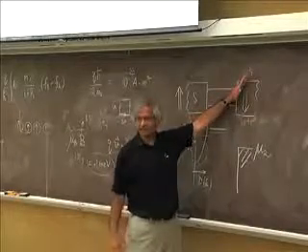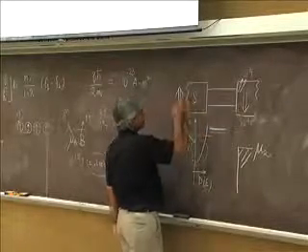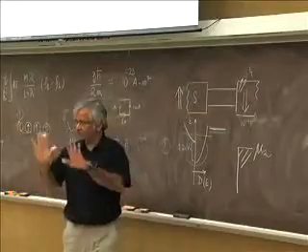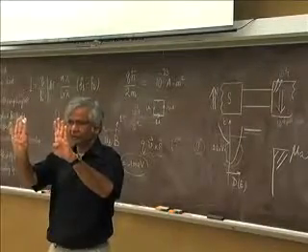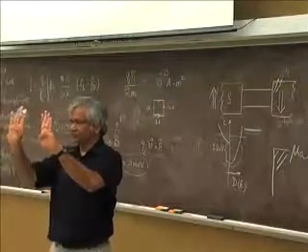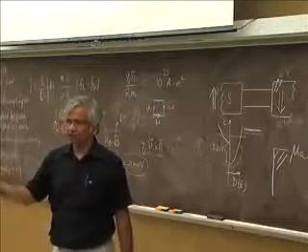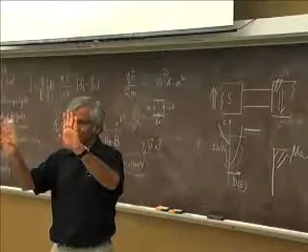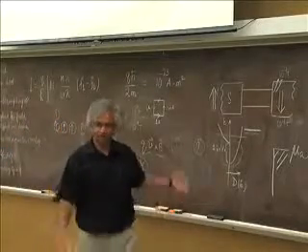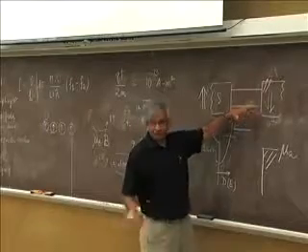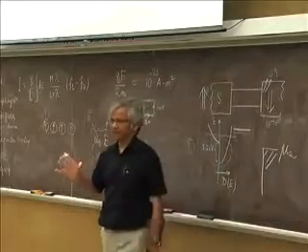But this little extra one is at some angle, which is why it's very important to have these two magnets have a little bit of an angle to them. So when they build these devices, they almost deliberately build in a little angle, because if they were exactly the same, you wouldn't get as much of an effect. You'd still get some because of thermal fluctuations, because it's never quite straight, so it jiggles around and feels some torque. And if it's a little hotter, it's easier to turn it, so you'll have a lower threshold current. But to get it to turn better with less current, they deliberately build in a little bit of an angle, because if it's exactly the same direction, nothing would happen.